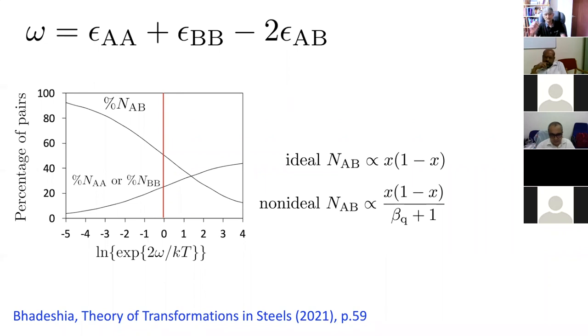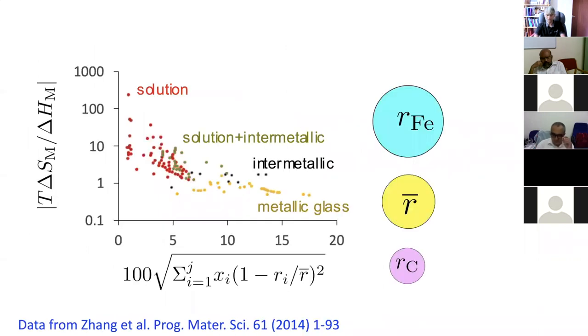The case I've illustrated here is for binary, but the quasi-chemical models can be of many levels of approximation, so you can handle multi-component systems and higher order interactions and all the rest of it. And you have to decide whether this is worth doing. So in general, the contribution of the ideal entropy of mixing to the free energy of mixing will be larger than what it really is, because the atoms will not be distributed at random. Unless you are dealing with a non-equilibrium structure of the solid solution, which has cooled rapidly from a high temperature.